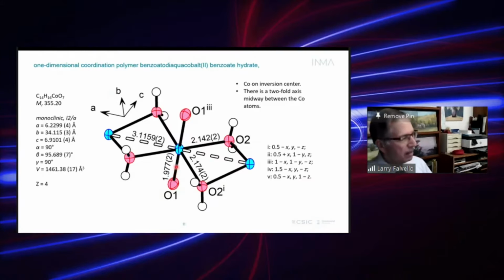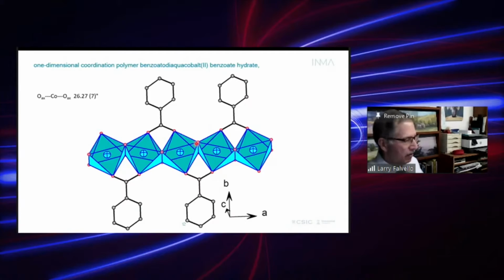And the cobalt coordination sphere is an octahedron, slightly compressed axially. This O1 is the benzoate oxygen, and its symmetry relative. It's compressed to the extent of this distance, and the axial cobalt oxygen distance is 92% of the average of the other two. And the octahedra are tilted with respect to each other. Maybe a bit of an optical illusion here, because the cobalt atoms are in a straight line. And depending on how you look at this, it looks like it may not be, because we get fooled by the tilting of the octahedra